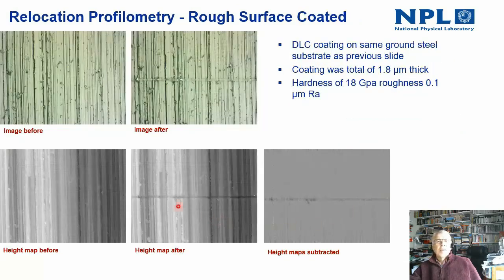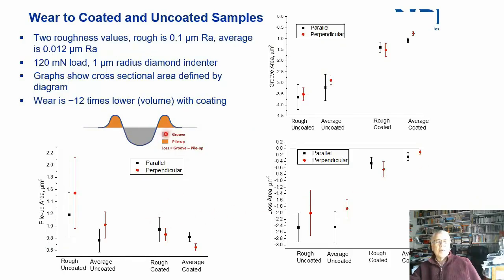So moving on to another example, this is now a coated surface, and again you've got the two images and the two height maps. You can see the much shallower scratch here, and it's interesting to note that this scratch is only about 40 nanometers deep here, and again you've got the registered and subtracted height maps giving you the information on just the scratch alone. You can then analyze that data, and typically in a scratch you have an area of the groove and an area of pile up, and then the loss area, the material that's actually removed, is the groove minus the pile up area. So if you look at the pile up area, then that's slightly higher for the rough